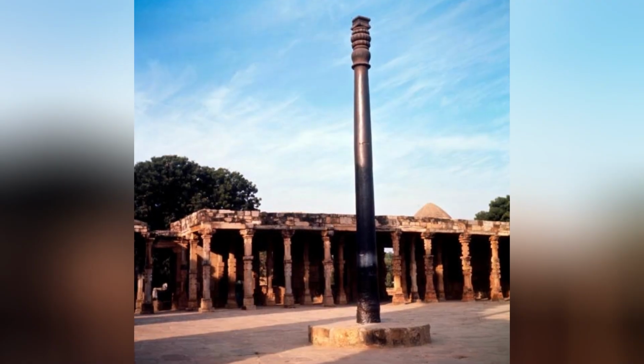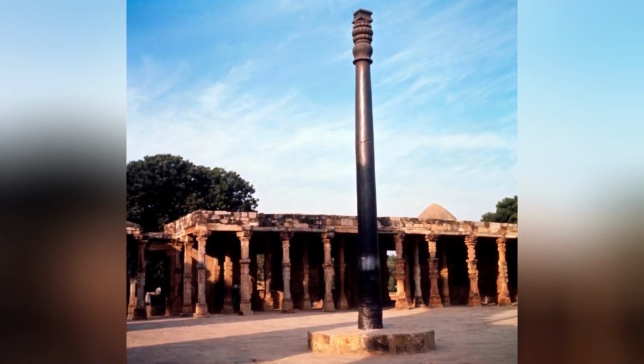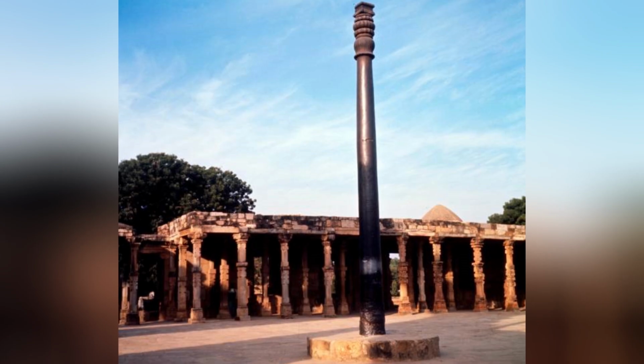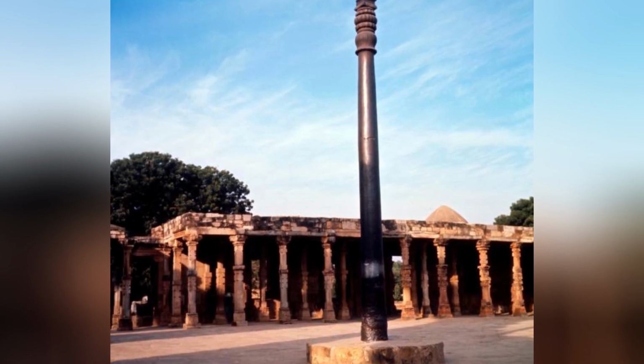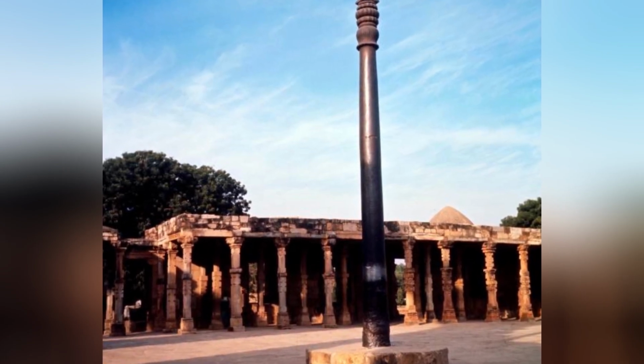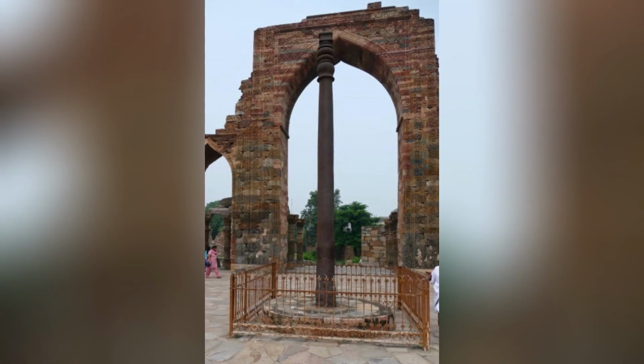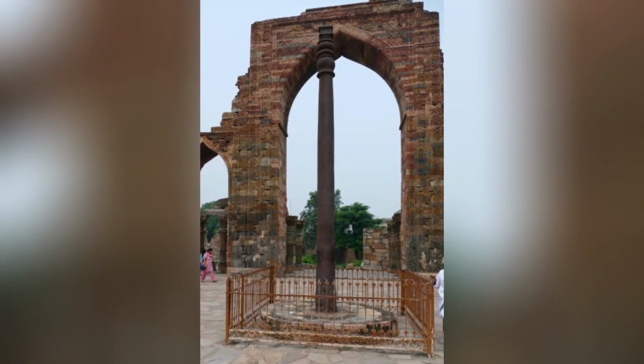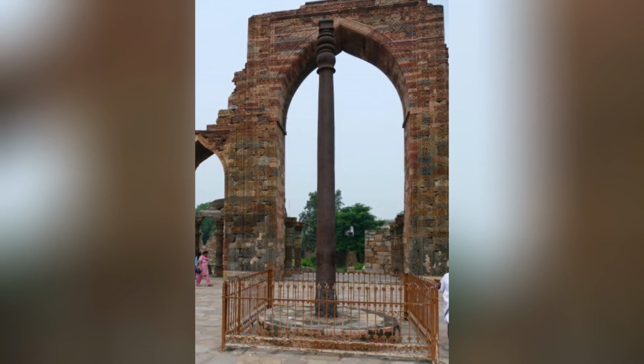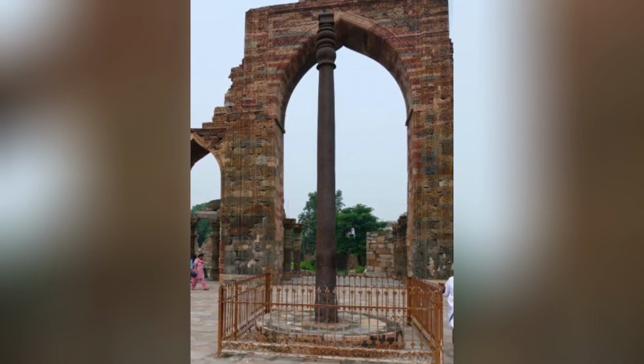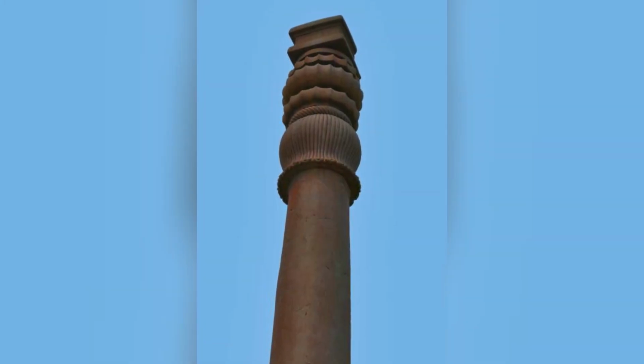During the wet season, moisture on the surface of the pillar dissolves the iron phosphate that has formed during the previous dry season, creating a solution of dissolved ions that reacts with the iron surface to form new misawite. During the dry season, the moisture evaporates and the misawite crystallizes on the surface, forming a dense, coherent film that resists further dissolution during the next wet season.